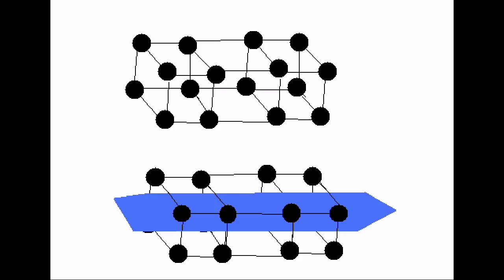If you place these phosphors between the parallel plates of a capacitor and then apply an alternating current, an electric field is formed across the length of these copper needles and electrons are swept back and forth. This is causing electrons to be accumulated on one side and holes on the other. When the field's reversed, then the holes are recombined and photons are emitted and the cycle continues.